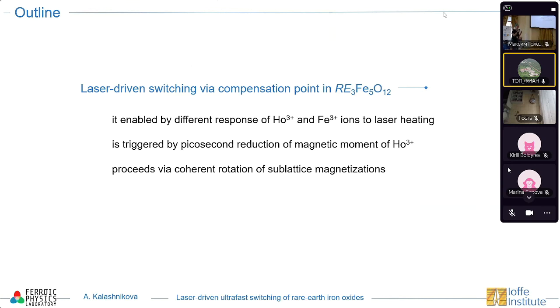I forgot to mention the excitation was at 400 nanometers wavelength. And we believe that it's still due to heating. And what is most important, we see that there is a fast drop of magnetization of holmium, and this triggers the whole dynamics, which allows switching via the compensation point.